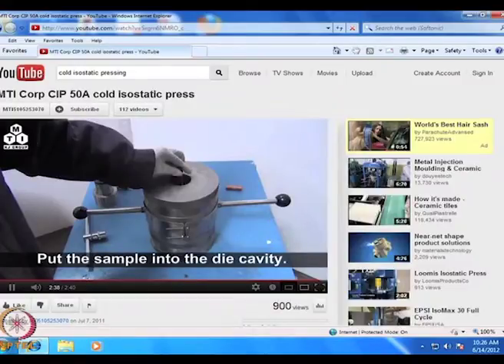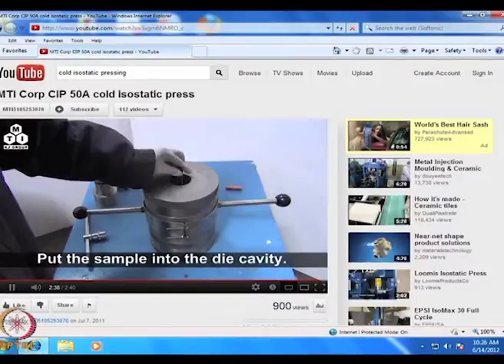Now, the advantage of this isostatic pressing is we get almost 100% theoretical density after firing, and before firing the porosity is hardly 0.5% or so, and there is no lack of uniformity in the structure right across the sintered body. Well, with cold isostatic pressing, one does have to sinter the body to get a sintered product. However, if we increase the temperature of this processing,